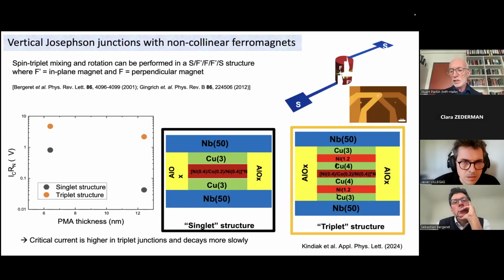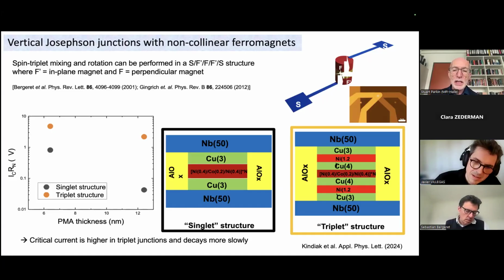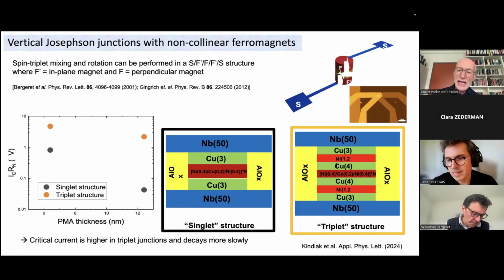What he has done is build vertical Josephson junctions. I understand that this Josephson seminar is based on Josephson concepts. In this junction, you can see in this cartoon, we have created a structure with conventional s-wave niobium electrodes. These are 50 nanometers thick, two of them. And in between, we've got some copper to separate the niobium from the red layer, which is a nickel-cobalt multilayer.